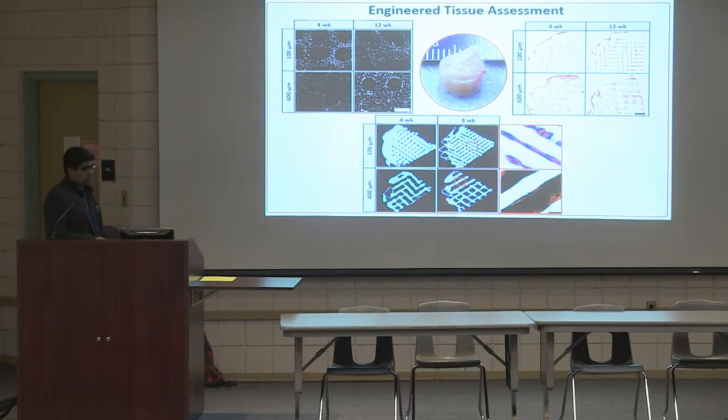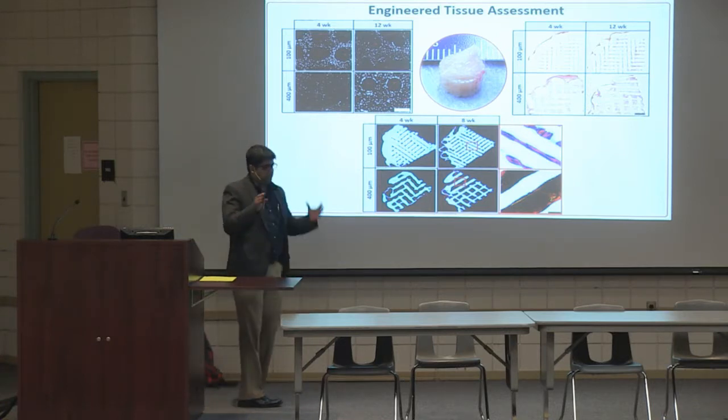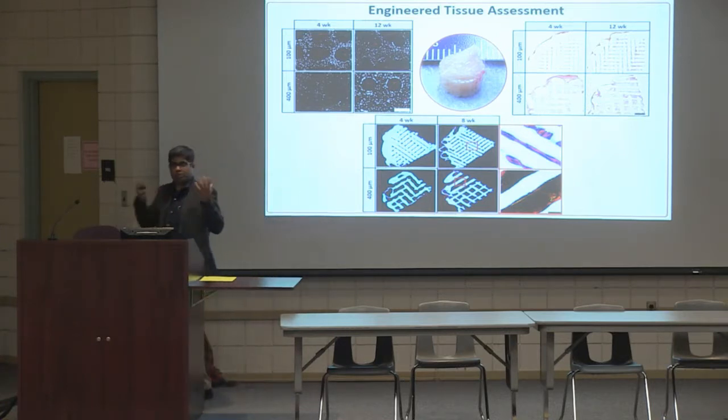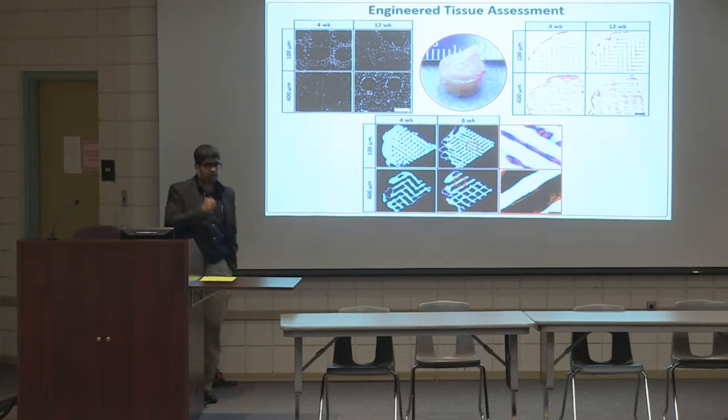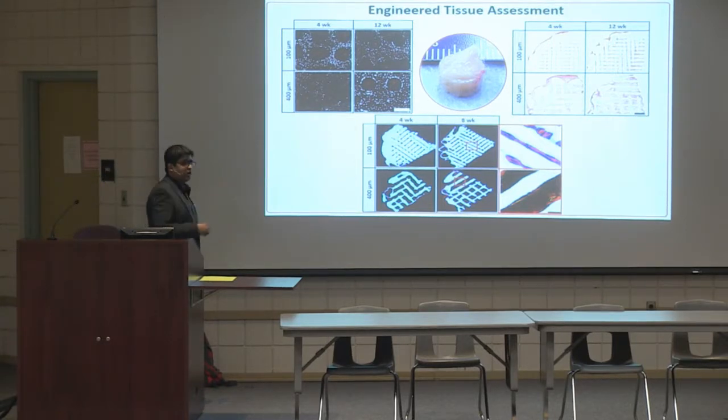It's just a snapshot of the results, but the main idea that I want you to get here is we had these 2 different designs, smaller pores, larger pores. What we found was the design did not affect the ability of cells to penetrate the scaffold. So even if the scaffold pores were very small, the size of your hair, cells were equally effective in getting in throughout the structure, which was really good. That was the first good news. And we were able to quantify it and show it statistically that yes, there's really no difference between these different designs and time points, so to speak.